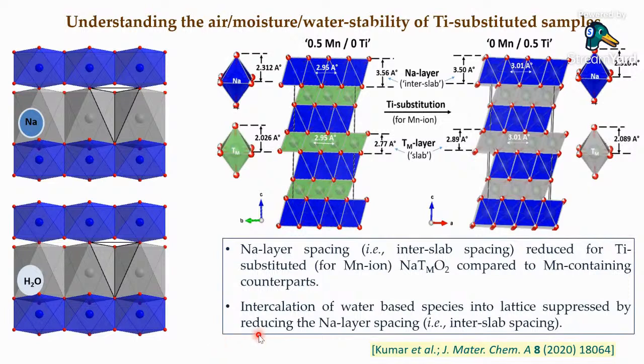When I say water insertion, I mean water based species like H+, H3O+. Now, with titanium substitution, what we found was that the sodium layer spacing, the sodium slab spacing, this particular spacing, got shrunk a little with the presence of titanium among the transition metal ions.